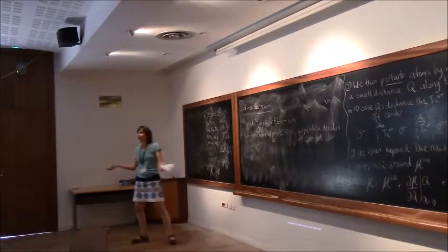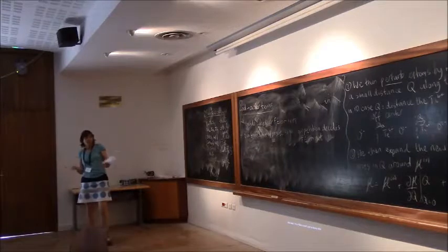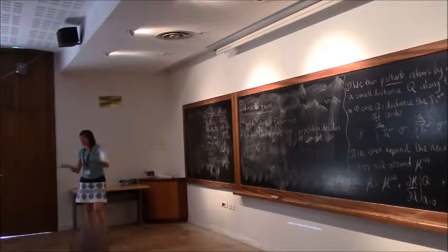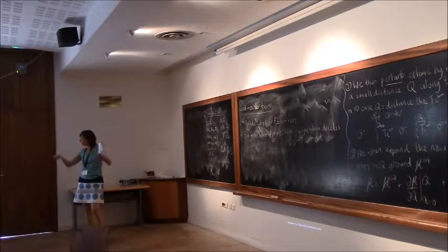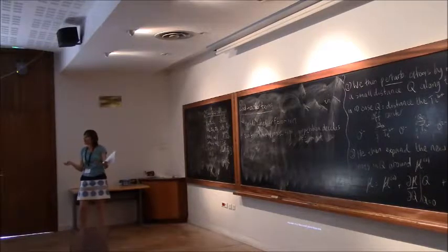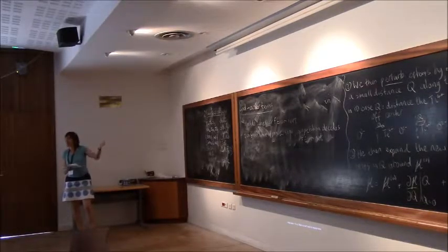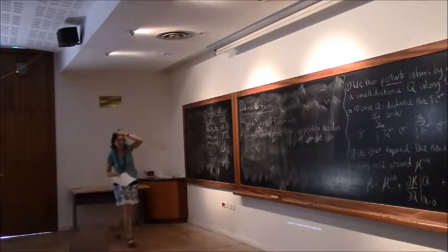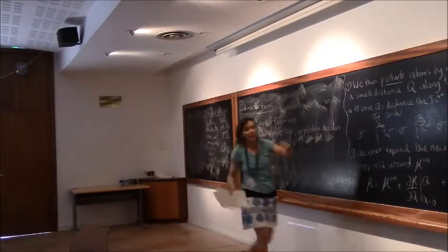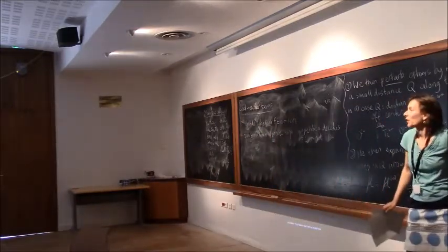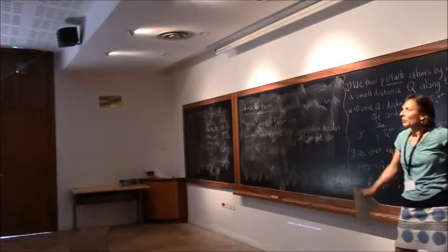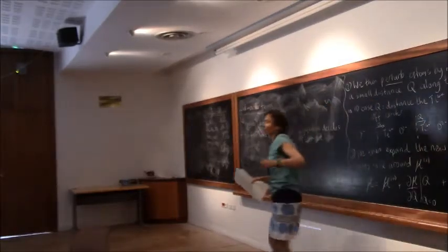Because I've solved my zeroth order Hamiltonian, my zeroth order Schrödinger equation, I found the energy ground state, and then keeping the electrons stuck in that ground state, I'm changing the Hamiltonian. That would be the same as keeping the Hamiltonian the same and changing the electrons away from the ground state. I'm making the electrons be the ground state for the wrong Hamiltonian. So this raises the energy. Conceptually we can see why this has to be positive. I'm moving the atoms and I'm not letting the electrons adjust.